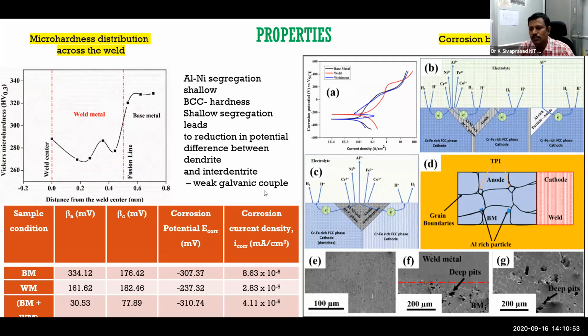And one professor from Tokyo University, Japan, suggested why don't you go for corrosion studies? That makes much difference. So yes, fine, we decided, and we saw that the corrosion properties are also significantly superior, almost comparable to that of the base metal, which is uncommon for high entropy alloys. Whereas the high entropy alloy weld has shown very, very good results.